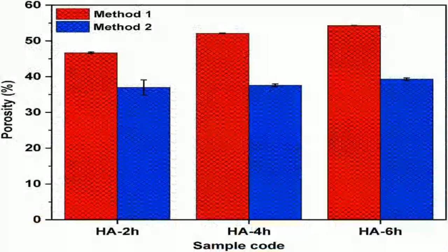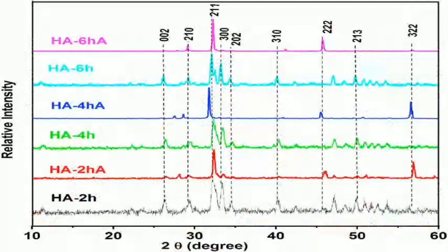Okay, that's impressive for hardness. But what about the trade-off? Did they lose all the porosity by sintering for longer? You'd often expect that, wouldn't you? More sintering usually means less pore space. Right. But here's the twist. The 6-hour dwell time didn't just give the highest hardness. It also gave the highest porosity among the tested times. Really? Both went up? It seems so for this specific material and process. They reported porosity values upwards of 50% for the 6-hour samples using some methods. Wow. So you get the hardness and the open structure needed for cells. It looks that way. A more open, interconnected pore structure, which is exactly what you want for tissue integration, getting nutrients in, waste out. It's kind of a win-win in this case.